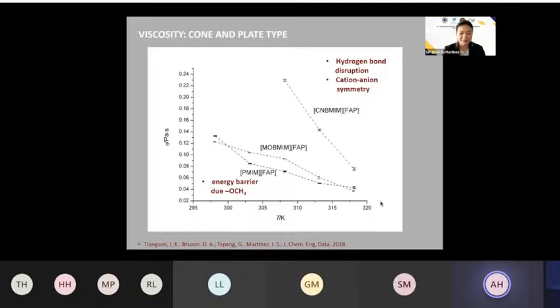And then, as you can see here, we have actually determined viscosity versus temperature. And we have compared the 3 ionic liquids in terms of how their viscosity changes with temperature. And you can see here that the nitrile functionalized one, once again, has the highest, probably because of the ion-ion symmetry or hydrogen bond disruption. And also, we think that we have lower viscosity for our methoxy functionalized ionic liquids due to the presence of this particular functional group, which actually lowers the energy barrier.